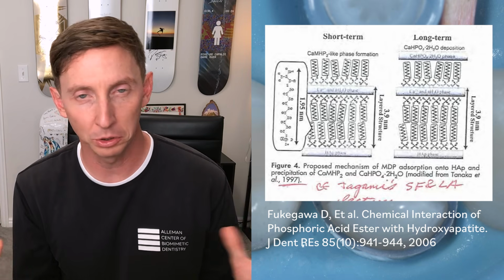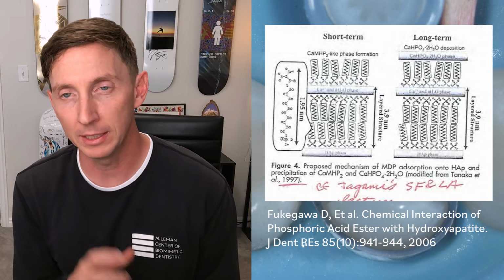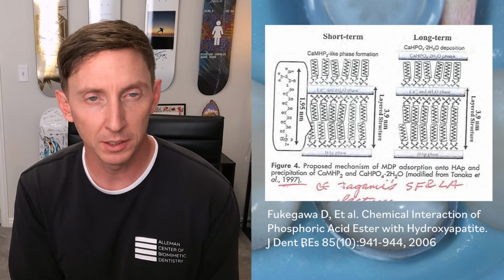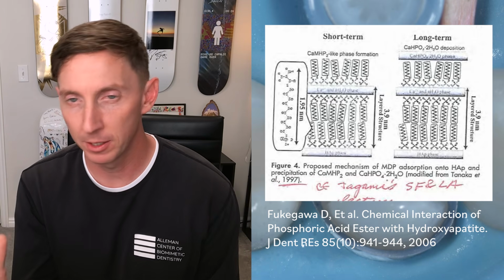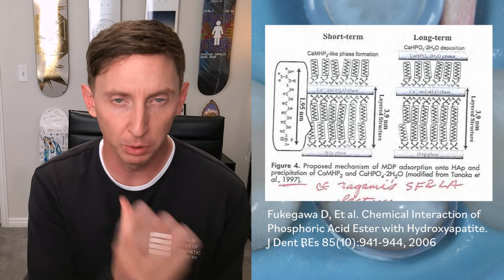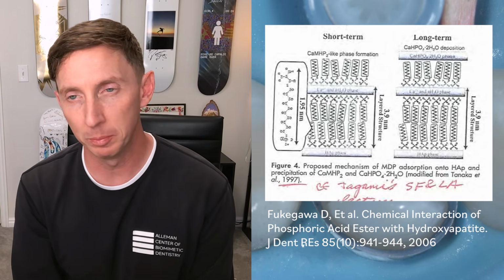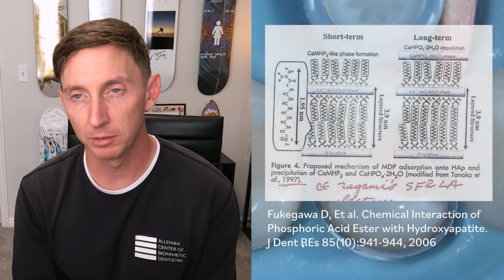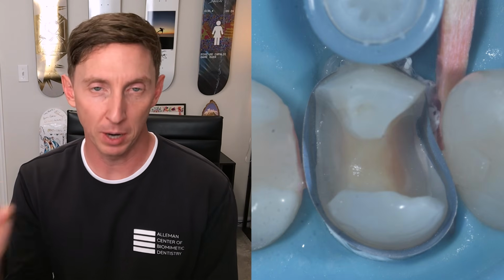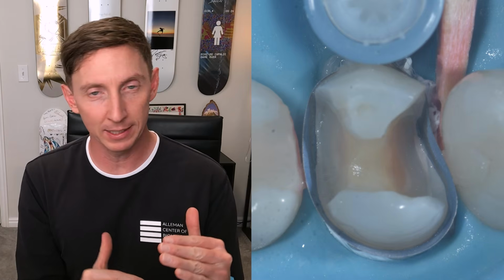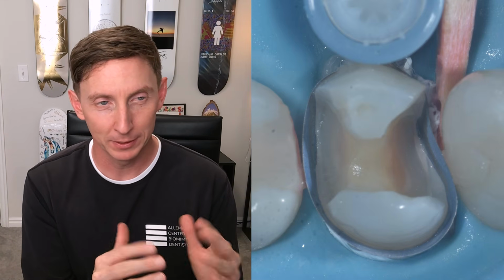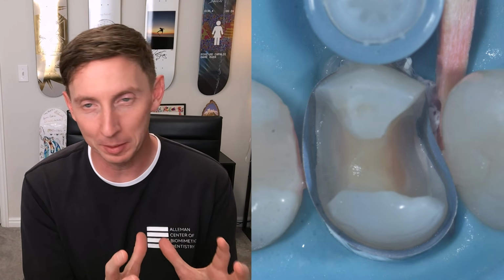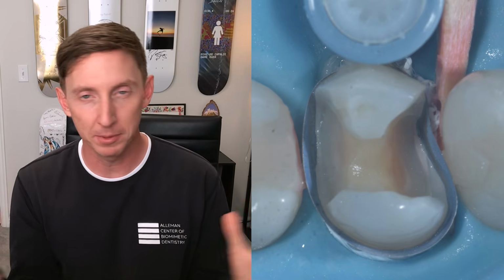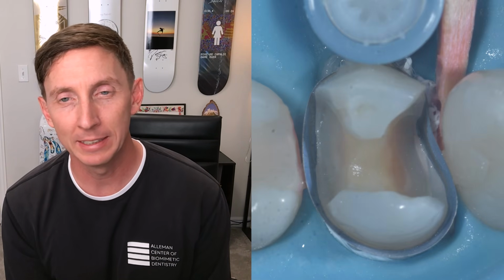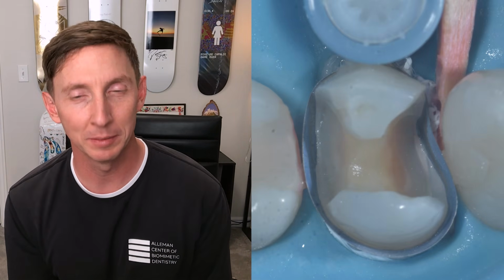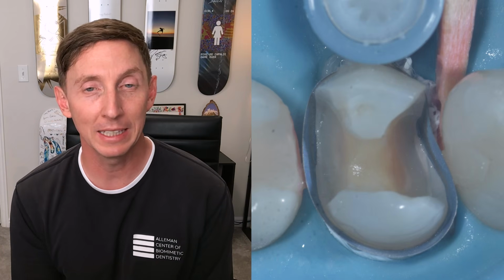It's truly, truly incredible to see these nano layers that Dr. Yoshida captured, as well as the proof that ionic bond could be established by Dr. Fukegawa. So after we've primed the dentin and we're creating this AD concept and forming an ionic bond that was just a pipe dream for the early dentist pioneers in bonding. Then we apply the adhesive.